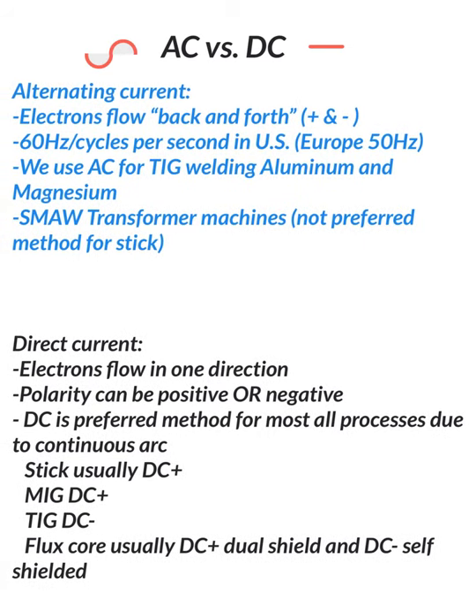Stick usually is DC positive. Most cases stick is DC positive. When in doubt, DC positive. If you're going on some thinner metals with maybe like a 6013, yes, you could use DC negative, but if you're training, just go positive.